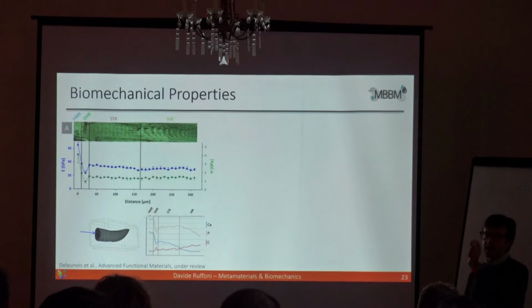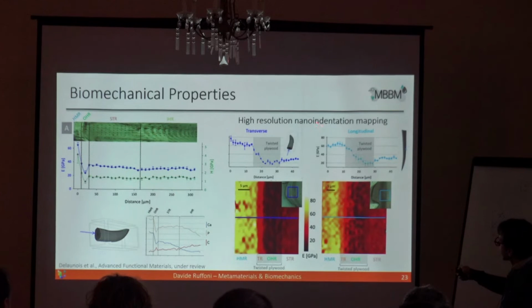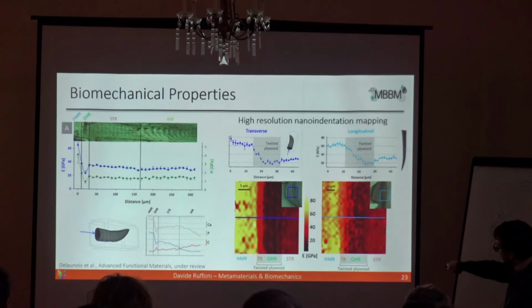Then we did some nano-indentation on a transverse cross section, moving from the outer highly mineralized layer to the inside, and we see that in the outer layer the tissue is very stiff, very hard. On the inside it is less so, and once again we saw this drop in properties corresponding to the interface between the highly mineralized tissue and the inside, which recalled a little bit what we see in the tendon-bone attachment. So there are 2 regions with quite dissimilar properties, which are joined by an even more compliant interface, and I think this was the first observation that was done in this respect. So we then went to a little higher resolution nano-indentation. By decreasing the space between the indents, we could characterize a little better what is happening between the highly mineralized, very stiff layer, the inside layer, and this region with lower mechanical properties.